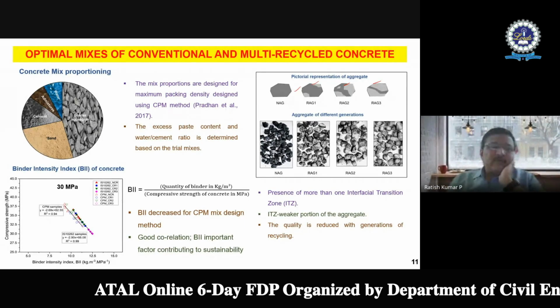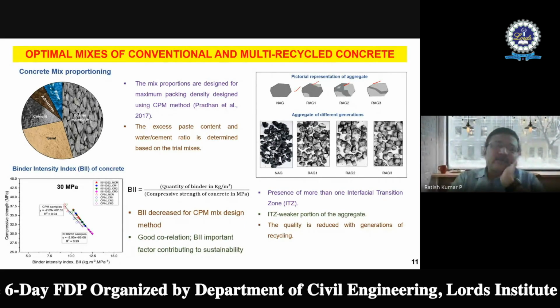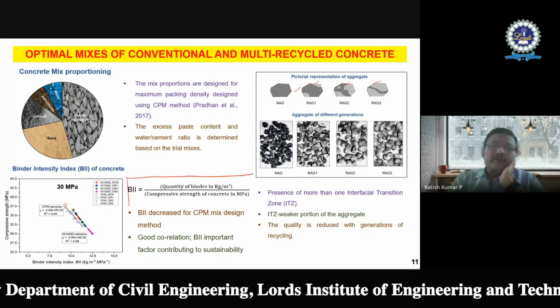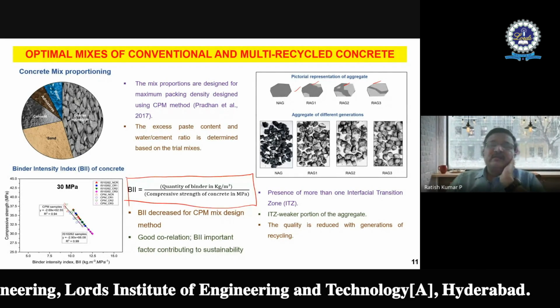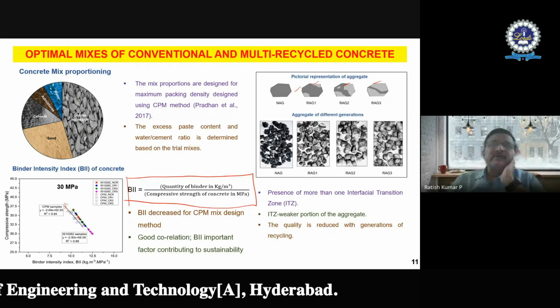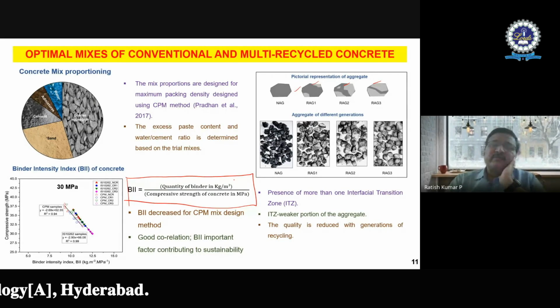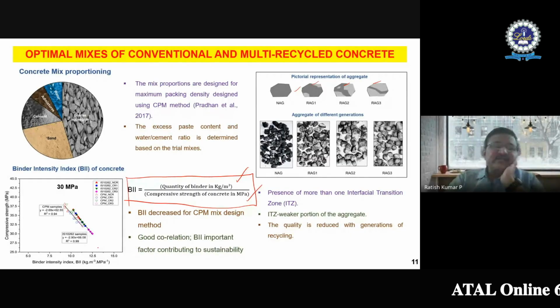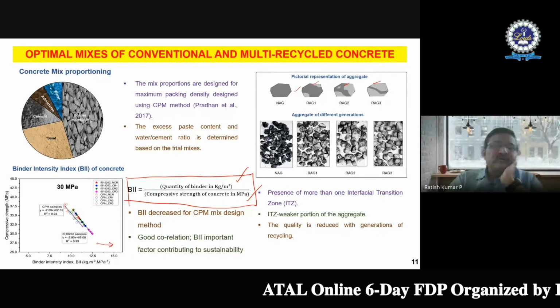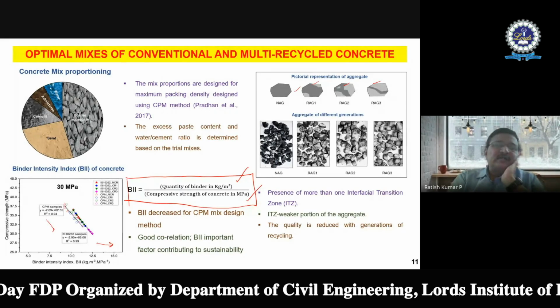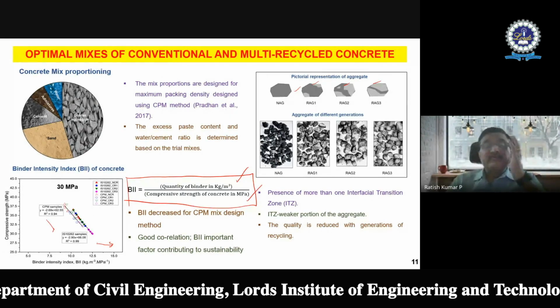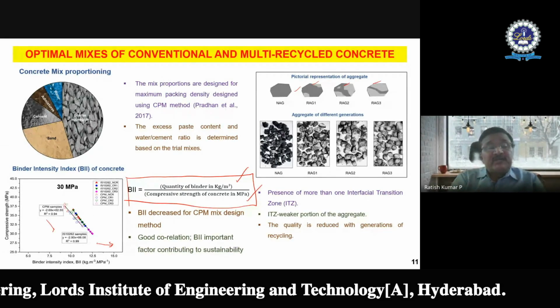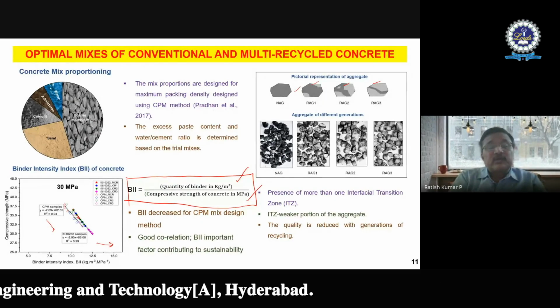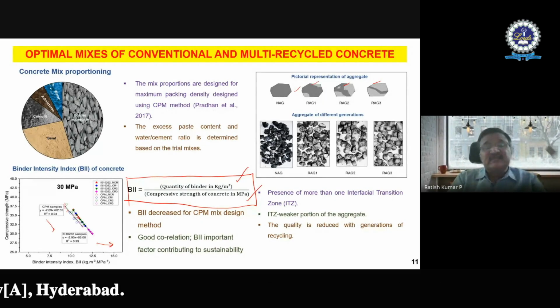And I have also come across, once I try to pack properly, then I try to estimate what is the binder intensity index. I can calculate the binder index as the quantity of the binder versus the compressive strength. You've noticed that as the binder intensity index goes to the right side, there's a drop in the compressive strength, and that depends upon the type of method which I'm trying to follow. So the advantage I'm trying to get is in case of the packing theories versus the